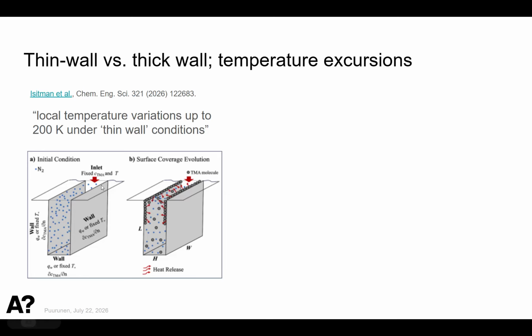The thick wall conditions would correspond to, well, wafers, for example a silicon wafer, where you grow a layer. Of course heat is being released in these reactions there as well, but there's the mass of silicon to absorb it, so you don't really get a much higher surface temperature. But if you have a thin wall condition where you have much less material that could absorb the heat, then you will increase the temperature of the system. And in these calculations, even 200 centigrade or Kelvin temperature increases were simulated.